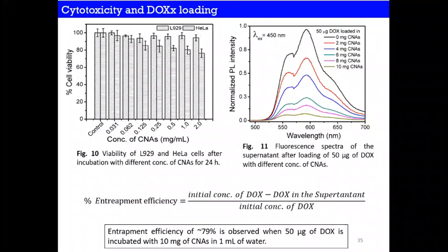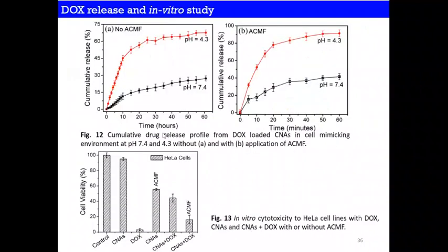However, we can get some cytotoxic effect in the HeLa cells, maybe due to, as I mentioned, reactive oxygen species, which may be one of the reasons. We have tested that one. Then we loaded the drug molecule, doxorubicin, and the entrapment or loading efficiency is found to be around 80% when 50 microgram of DOX is incubated with 10 mg of nanomaterials in 1 ml of water. And you can see that this material is also showing some pH responsive release.